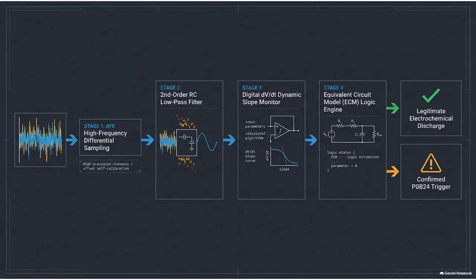But if chunks of the material are falling off, wouldn't the cell just lose overall capacity? Why does it trigger this violent dynamic fault when you step on the gas? Because of localized overworking. Think about it. If 20% of your active material has detached, the remaining 80% has to work significantly harder to deliver the same amount of requested power. Oh, I see. So when you demand a sudden heavy discharge, like slamming the pedal to pass that truck, you're asking the cell to produce a massive amount of chemical energy instantly. And the remaining 80% just panics. The diminished active material physically can't keep up with the chemical reaction rate required.